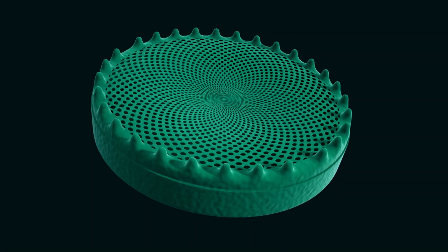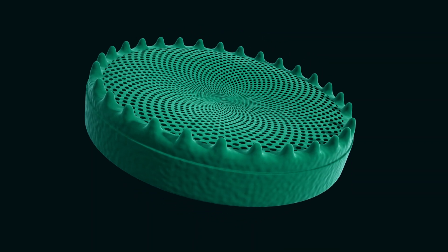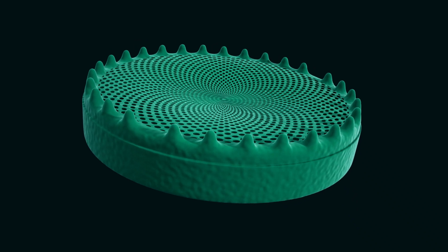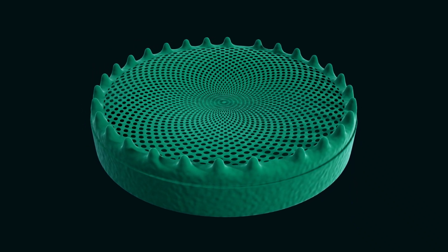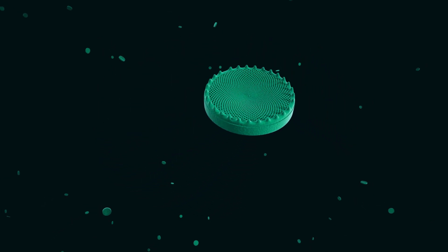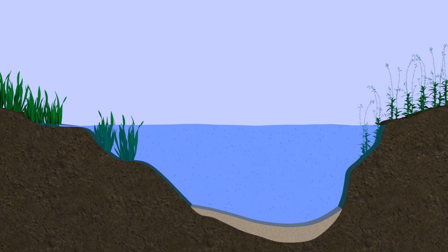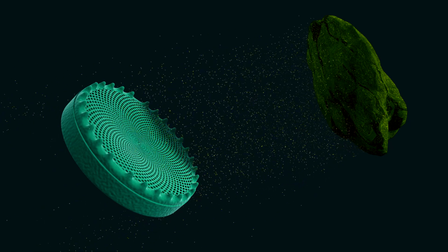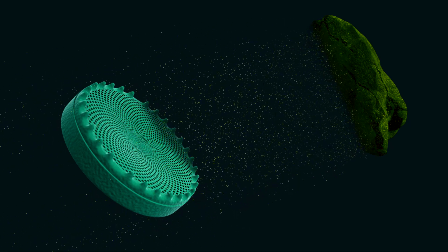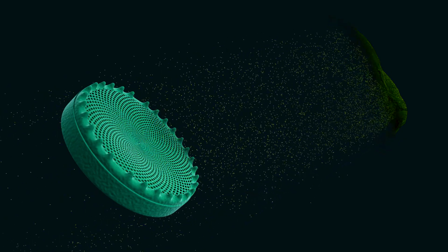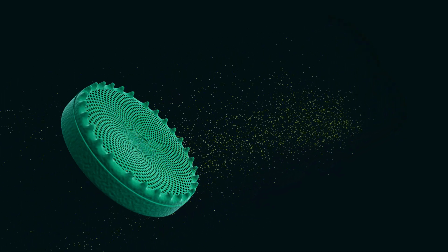So one of the examples we're looking at in terms of materials is silica, which is SiO2. And there are microalgae called diatoms, which grow in ponds and also in drinking water sometimes. They produce biological silica. So diatoms selectively uptake the precursor for silica, which is essentially dissolved rocks in any water environments. It then uptakes that and concentrates it within the cell, and those concentrated pools of the precursor are taken to the site of silica deposition.